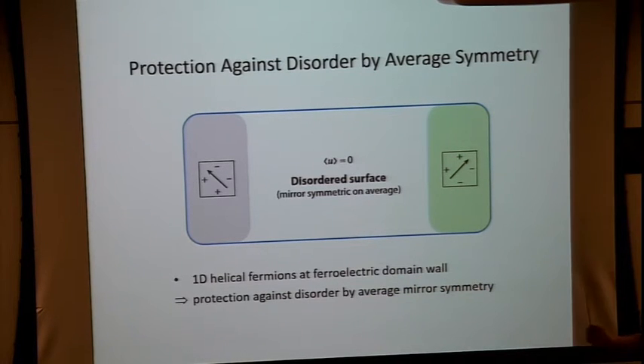Let me also comment on that. There's a difference if I compare the topological insulator surface and the topological crystalline insulator surface. In both cases, the surface states are metallic, but for different reasons. In the topological insulator case, going back to Rahul's question, the surface states are metallic because they have an anomaly. In this case, the surface states are metallic because gapped surfaces, if I break the mirror symmetry, are topologically different. So the surface, when mirror symmetry is on average present, is self-tuned to the topological phase transition between a 2D normal insulator and a 2D quantum spin Hall insulator. So it's basically delocalization by being critical.